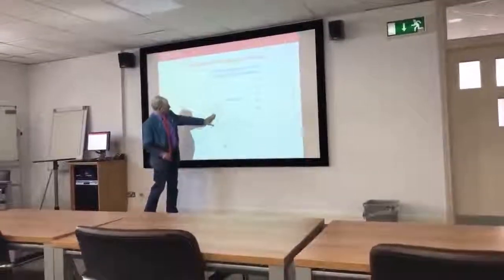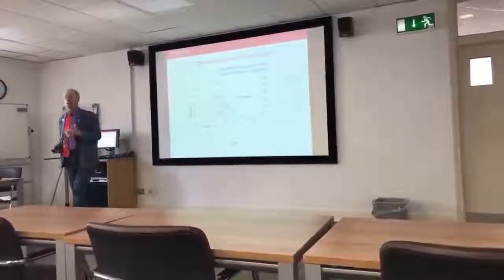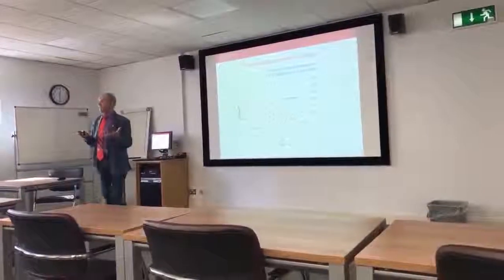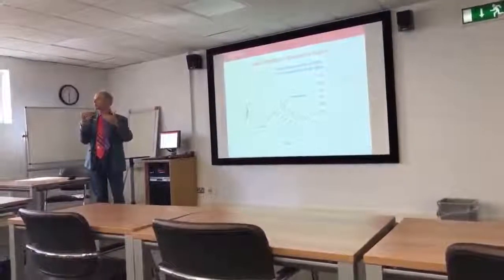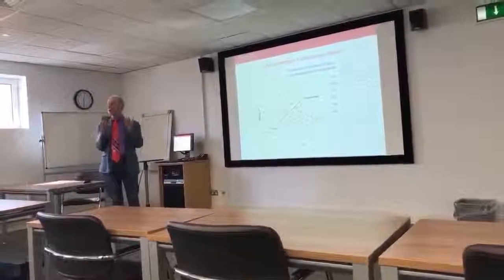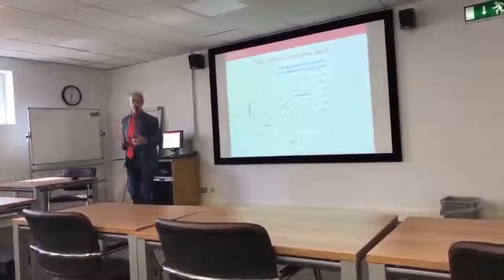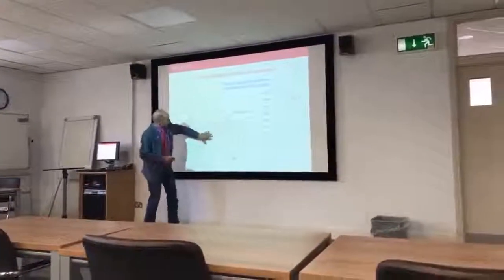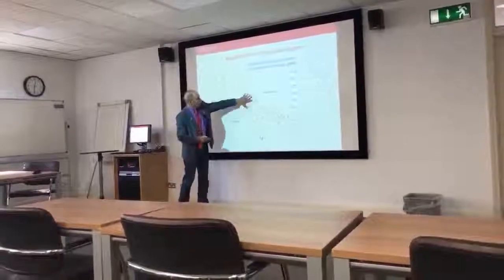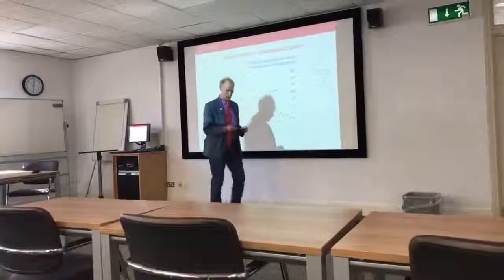And the key thing to note is as the sugar becomes more complex, the rate of matrix relaxation goes up. So the matrix is more mobile, the more complicated it is. Well, that makes sense because you're making a glassy state out of the more complicated molecules. There's a lot more local motion occurring, what we call beta relaxations, within the glass. And those beta relaxations are actually interacting with the probe, quenching it. And so we've got a measure of how rapidly the matrix is moving to quench it. And this very clearly indicates that within this glassy state, you've got a considerable amount of dynamic heterogeneity occurring, and there's more dynamics the more complicated the matrix, the larger the molecule in which the matrix is made.